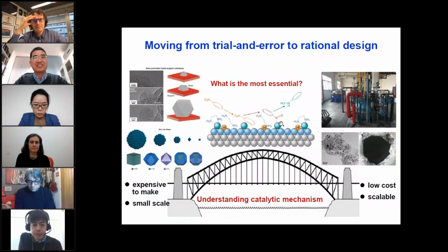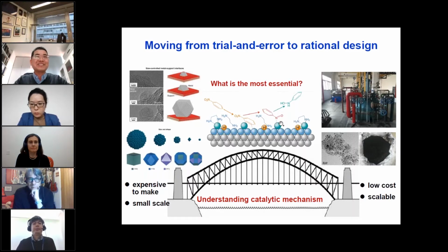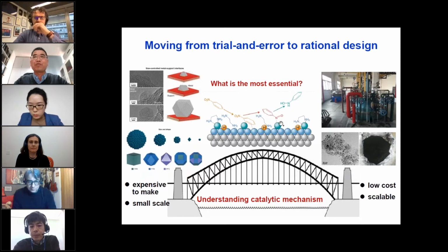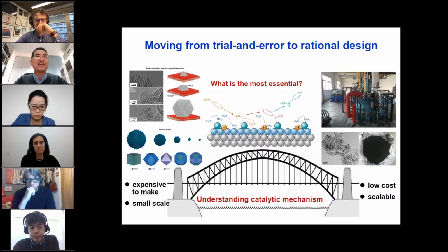So how can we tackle this challenge? Normally, we consider one really effective strategy is to prepare model catalysts with controllable and well-defined parameters, for example size, morphology, exposed surface, and also metal-support interface. Then we can use all these materials as model systems to understand how these parameters influence catalysis. Here I would like to give you one example. I think Kensaku already mentioned that if we have organic modifiers on the surface, like ionomers, we might introduce some poisoning effect. But after years of study, we realized that if we modify some noble metal catalysts with organic modifiers like ethylenediamine, we can introduce a significant electronic change on the metal surface.